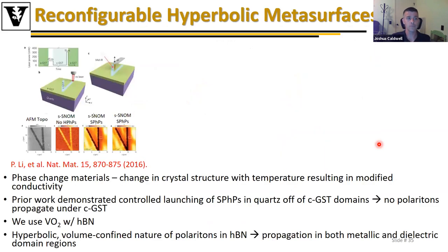Okay, so now, hopefully if I can steal a couple extra minutes due to my computer snafu, we were motivated by some work from Thomas Taubner, where he used surface phonon polaritons on the surface of quartz and used the phase change material GST to manipulate those modes. He was able to do laser writing to convert amorphous to crystalline GST and thus control the propagation of these phonon polaritons. One of the challenges, though, was that because the surface phonon polariton is on the surface of the quartz, in the crystalline state the GST is quite lossy in the spectral region and therefore doesn't support the polariton mode.